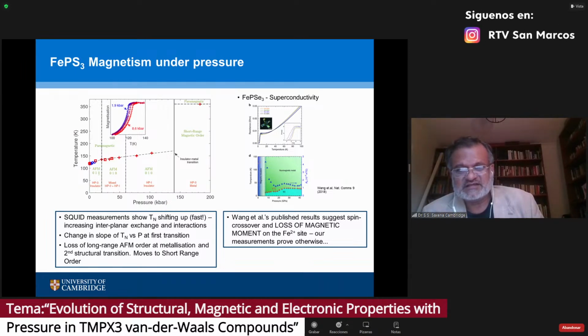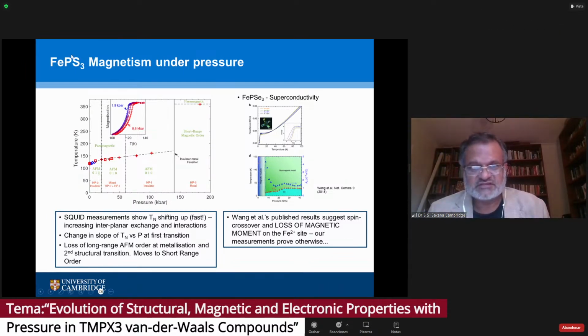But what is quite tantalizing is that you have a neighboring material. So this is sulfur 3. If you go to selenium 3, you actually see that exactly at this kind of pressure, it follows more or less the same story. But when this collapse happens, it becomes superconducting. And we have been investigating this as well. So far, our neutron and structural work shows that this material probably loses magnetism. Unlike this one, which retains short-range magnetism, this one loses magnetism